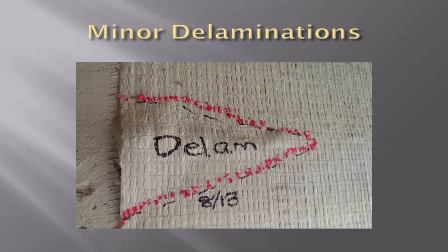Here's a delam similar to the previous where there's a kink in the fiber when they were installing it. You can see that if they would have filled that kink with an epoxy or more binder, it could have kind of bridged that gap. But now when you have a delam, the stress transfer won't go across that delamination. So therefore you've created a stress riser. So you mark them, you date them, and you see if they get worse.